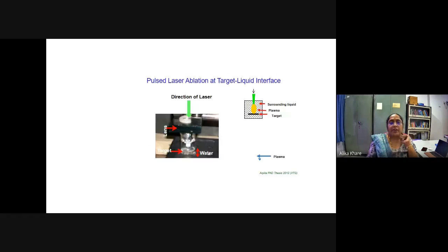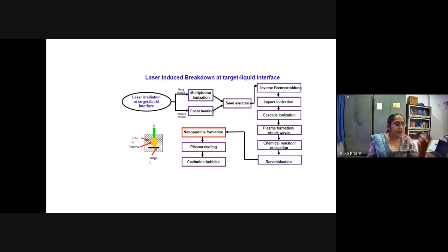We can also have the target placed in the liquid at the bottom. This photograph is slightly poor quality. So the target is at the bottom, and then the laser is focused from the top. Here is the photograph of the plasma. When the laser is focused, the target material comes out in the form of plasma, and the liquid is also breaking down in the form of plasma. So this complete elongated line is the formation of the plasma. This is the entire process of laser induced breakdown at the target liquid interface.